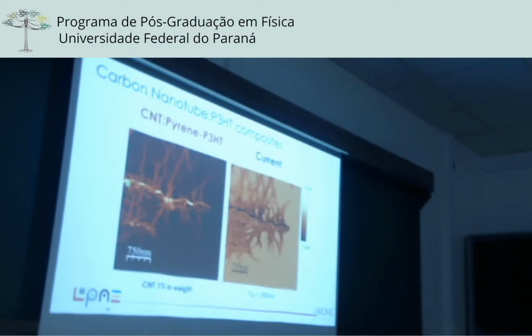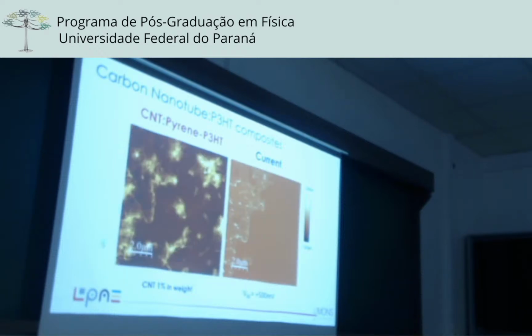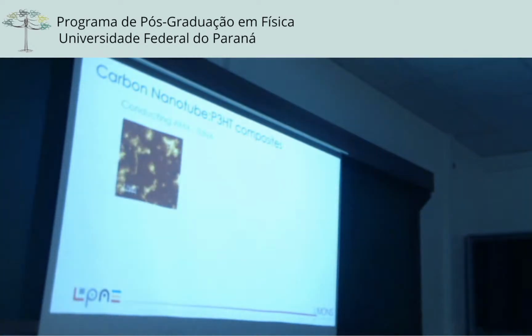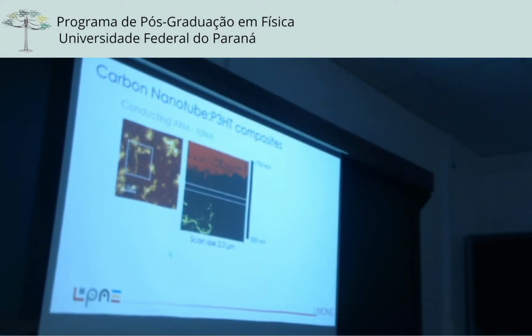If you focus on this region, this is the curly carbon nanotube here, this is the current, and we have the P3HT growing perpendicular to this carbon nanotube with a width of 16 nanometers, as we saw before. In this case, the electrode is on the left side. This is the topography, this is the current. Now the voltage is positive. And because this aggregate is not connected to the electrode, there is no current. It's one way to see the percolation of the charges through the system. So we focused on this and changed the voltage from the bottom to the top. So we have positive, then no current, and then positive again.